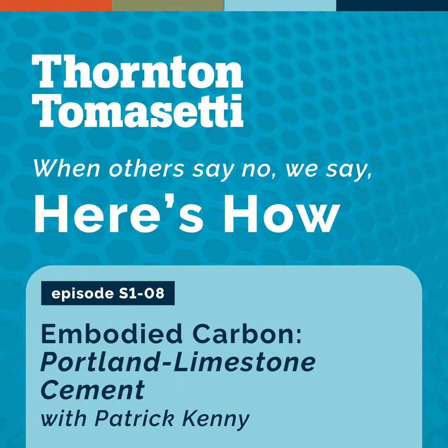Now, all that heat has a large carbon emission. The ASTM C150 standard allows a small amount of raw limestone, which is made with no processing or cooking, to be added to the clinker. But no more than 5% of the final product can be this raw limestone. In 2012, Type 1L, or Portland Limestone Cement, or PLC, was added to ASTM C595, which is the blended cement specification. In this specification, there has to be at least 5% limestone content, and it can go up to 15%.